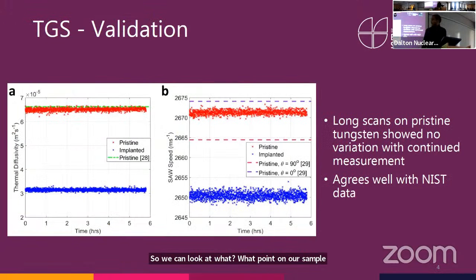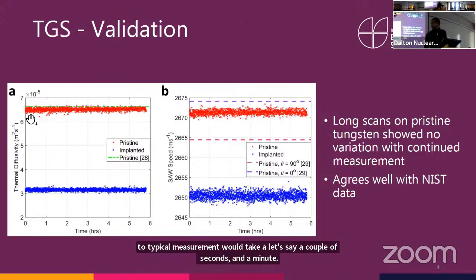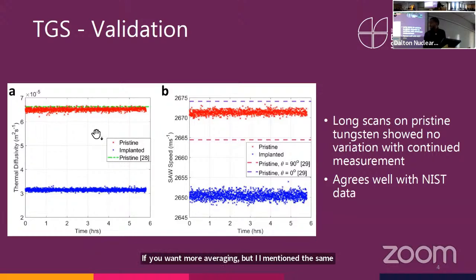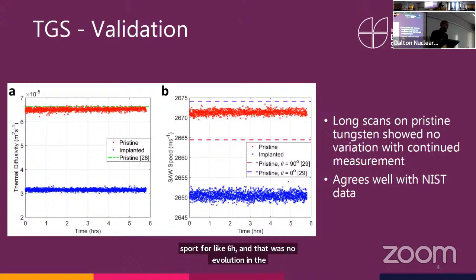A question I quite often get asked is, do the lasers affect your measurement, or do the lasers heat up your sample and so on? So this is again a pure tungsten sample and an implanted tungsten sample, and a typical measurement would take a couple of seconds, or a minute if you want more averaging. But I measured the same spot for 6 hours, and there was no evolution in the measurement, which shows that the lasers don't affect it. And this is for your thermal diffusivity, and this is for your surface acoustic wave speed.